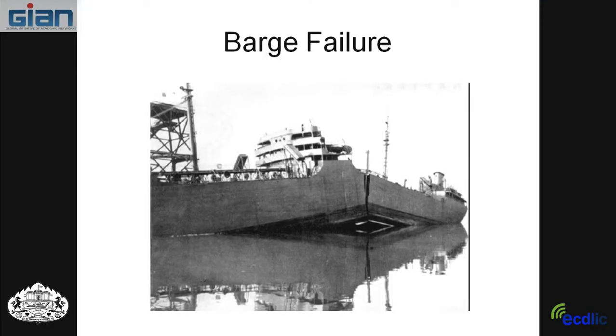And as they started to sail across the North Atlantic where the water was cold, some of the ships failed. Of more than 2,000 ships, some 400 had cracking problems, some 90 had bad cracking problems, and some 20 of them had complete failure. Complete failure was a little bit like the Titanic. If you've seen the Titanic movie, that came around about 10 years ago or so, people saw how it broke in half and went into the water. These went down quicker. They didn't have a lot of actors dragging out the failure, but broke in two, whoomp, down in the ocean.